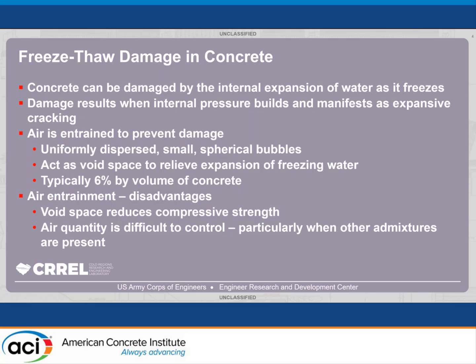The other downside that we've seen, especially in the lab, is that your air quantity is very difficult to control. We typically have to do several test mixtures to reach that target 6% or target 7%, whatever it is for our needs. And it's especially difficult when you have other admixtures in the mixture as well. So with this project, what we're talking about is incorporating this air entrainment technology with several other freeze protection additives. In our research, we've seen a lot of struggle in trying to meet our target air entrainment. And so when the technology of the SAP came up, we were really interested in seeing if it could work for us.